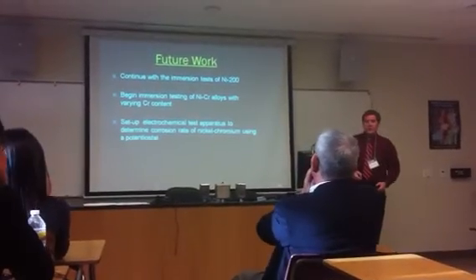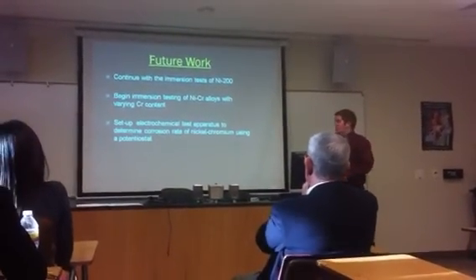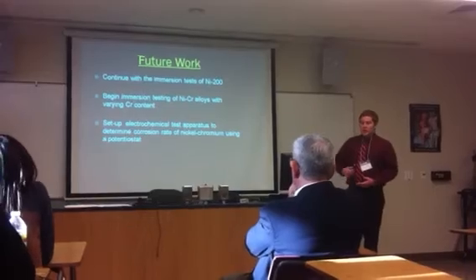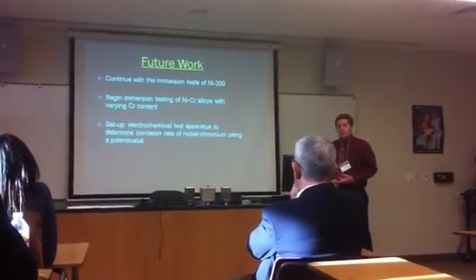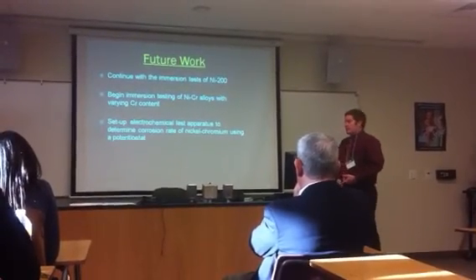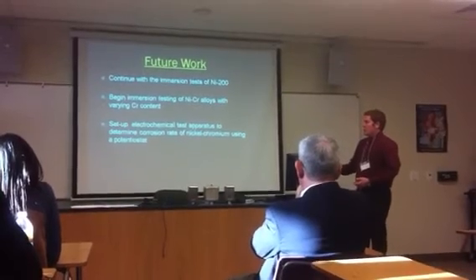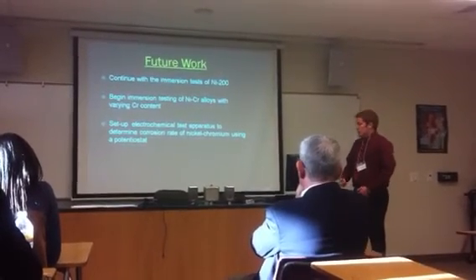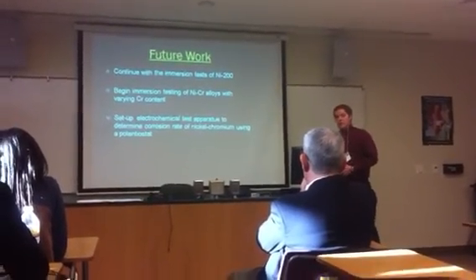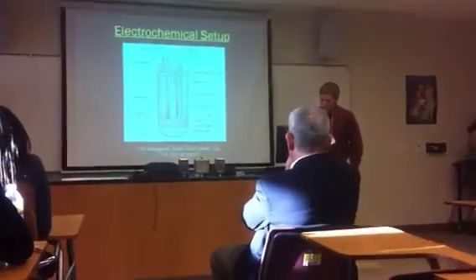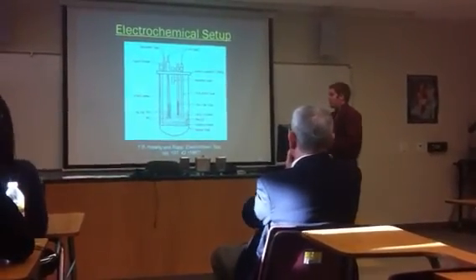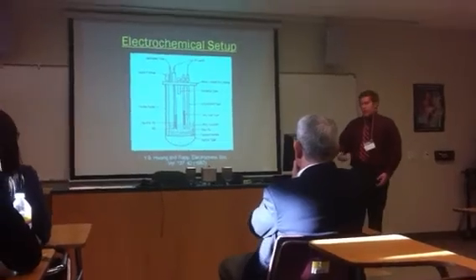So for our future work on the project, we'll be continuing with the immersion testing of the nickel 200. We'll begin immersion testing nickel chromium alloys with varying chromium content, and we'll be setting up an electrochemical test apparatus to determine the corrosion rate of the nickel chromium using a potentiostat. Here is the electrochemical setup that we hope to model our next project after.